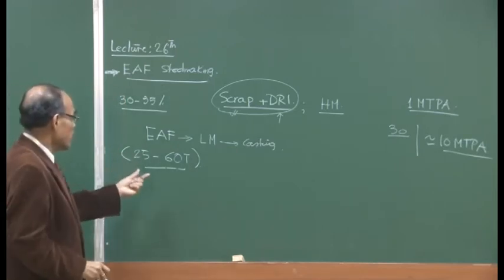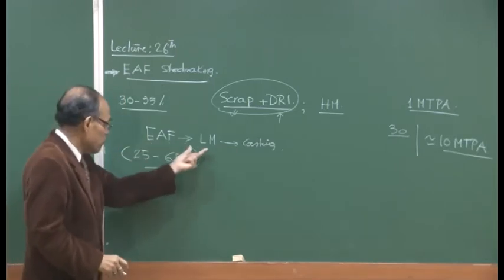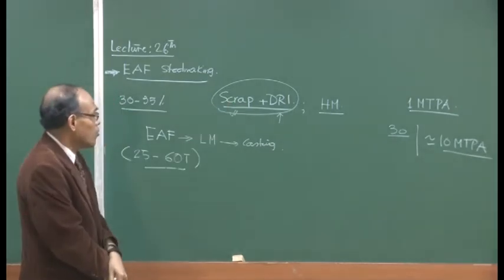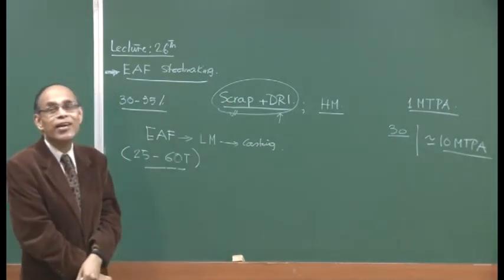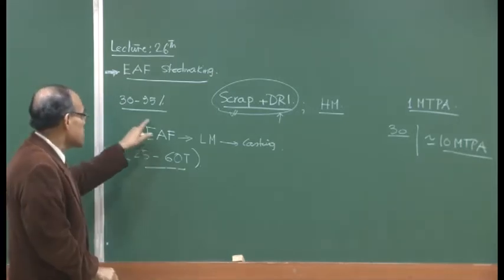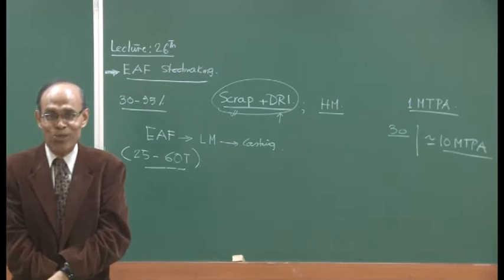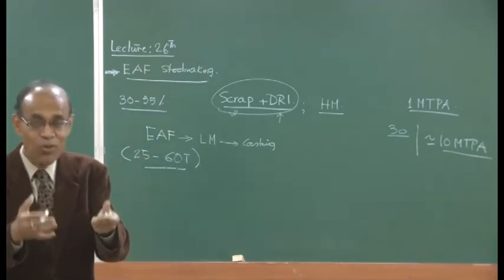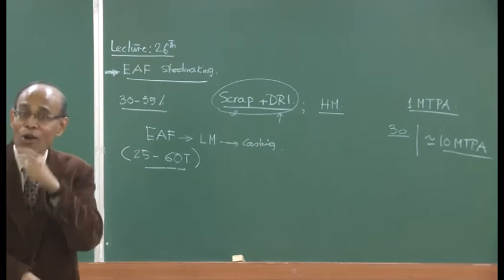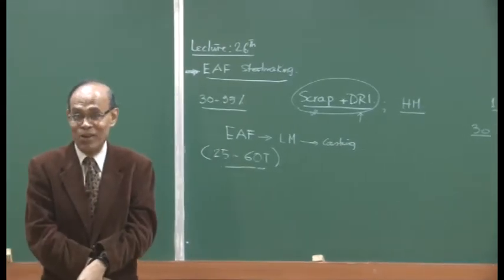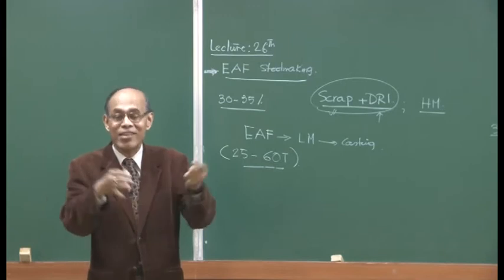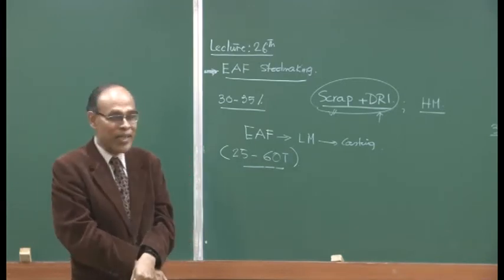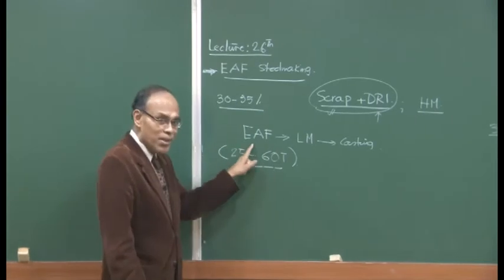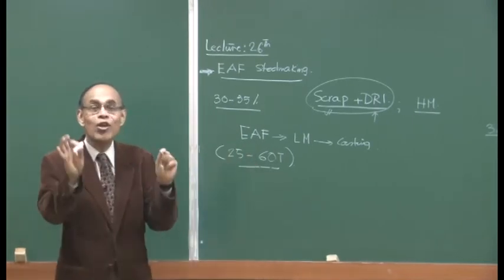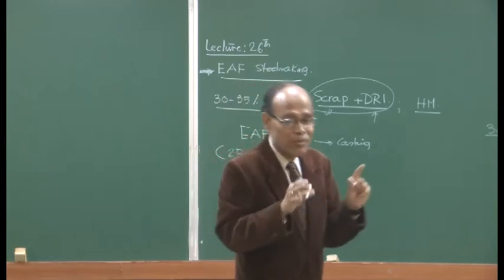So, if you take DRI or scrap, you must understand that you do not have much carbon or silicon left. Therefore, this is a non-autogenous process, and the electric arc furnace basically tells you that you have to supply energy from the outside, but in BOF we have seen that no energy is supplied from outside. The heat is generated because of the chemical reactions, and that sustains the process. Okay? Although the thermodynamics of steel making are identical, because you are talking about 1600 degrees centigrade and close to 1 atmosphere pressure, okay?